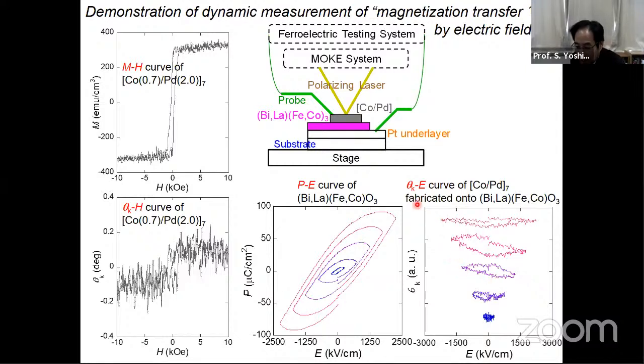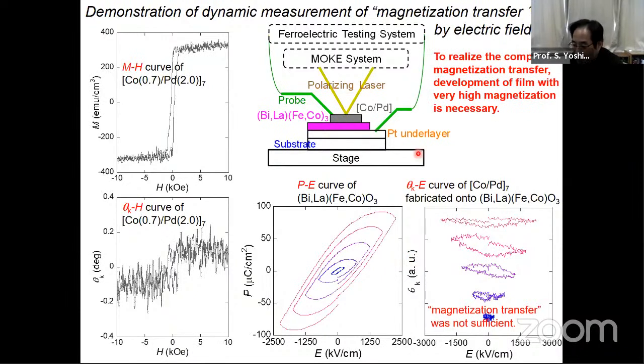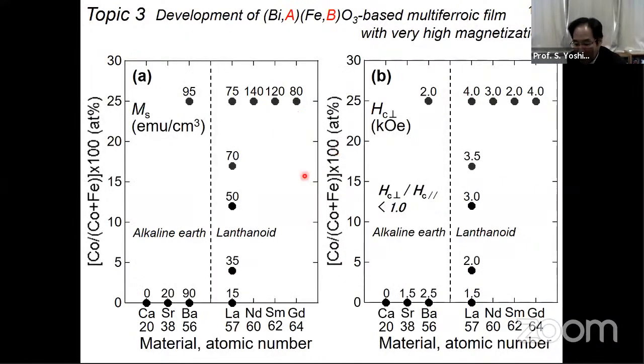So this indicates that the magnetization direction of this material was measured during the application of the electric field. But the magnetization transfer was not sufficient to realize the complete magnetization transfer. Development of film with very high saturation magnetization is necessary. So, okay, I'll move to topic 3, development of new BiFeO3-based multiferroic material with very high magnetization.